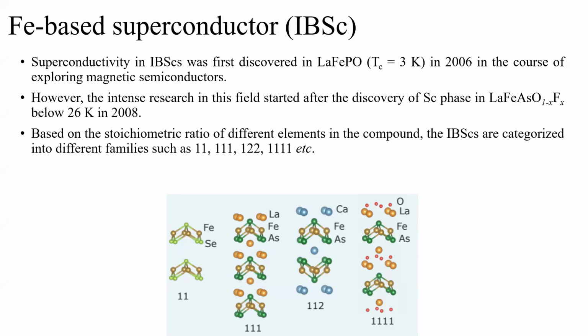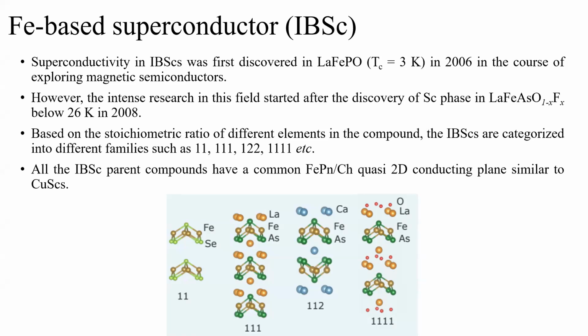So it's basically depending on the stoichiometric ratio those elements have in these compounds. Similar to the copper-based compounds, these compounds also have many common features. One most important common feature is this quasi two-dimensional iron pnictide or chalcogenide layer, which is a conducting layer, and the other layers, which in the 112 compound is the calcium layer, or in the 1111 compound La or oxygen layer, don't have any significant amount of density close to Fermi energy. So mostly the conductivity or superconducting phase that we observe in these compounds comes from the quasi two-dimensional layers.